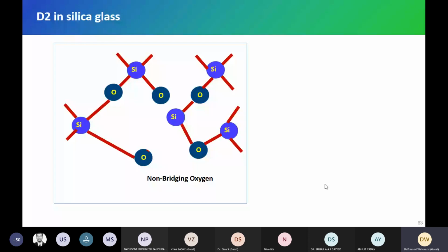So what we do to avoid this futuristic problem is put deuterium here, D. D is the same as hydrogen. So D makes a bond with O. Now we have OD, not OH. This also creates attenuation. It's not that it is free of attenuation. This also creates a loss in the optical fiber, but that loss is in a very high wavelength region, that is 1.9 micron. We don't use that region right now for communication. Right now we don't have that problem. We use 1.55 micron, we use 1.3 micron bands. If you put D there, we get attenuation at 1.9 micron, the higher band. If you add H there, OH, it will give attenuation at 1.38 micron.